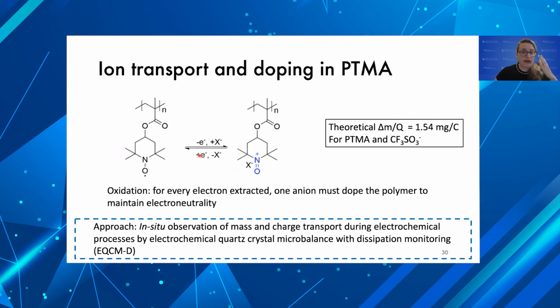So now that you understand how electrons transport, we want to understand how the ions transport. And to do that, my group has applied electrochemical quartz crystal microbalance with dissipation monitoring. In this technique, we measure changes in mass of the electrode while we charge and discharge the polymer. So it's like doing a big mass balance, for all you chemical engineers. If we're going to do a mass balance, we need to think about what mass we expect to see. For every coulomb of electrons that transfer, we expect to see a 1.54 milligram change in mass if the anion is a triflate. So that represents some theoretical value, assuming the doping process takes place the way we thought it did.